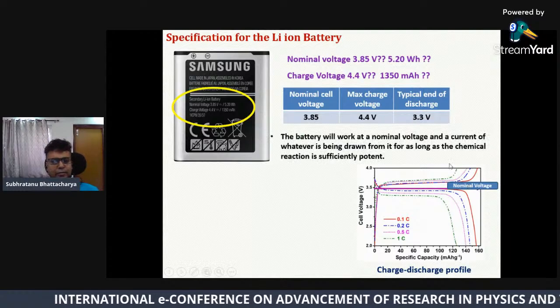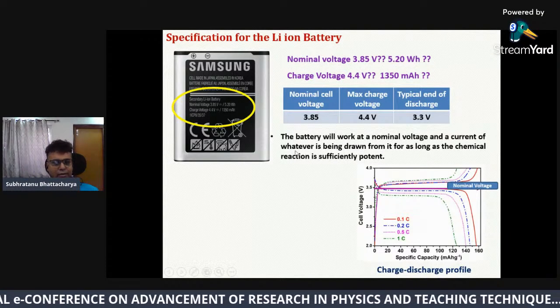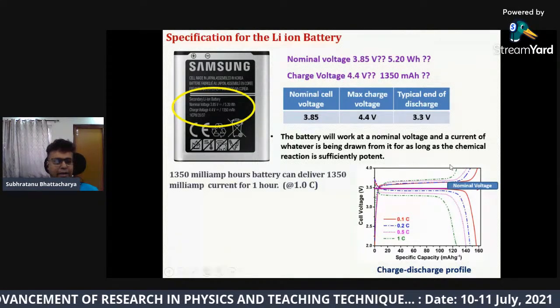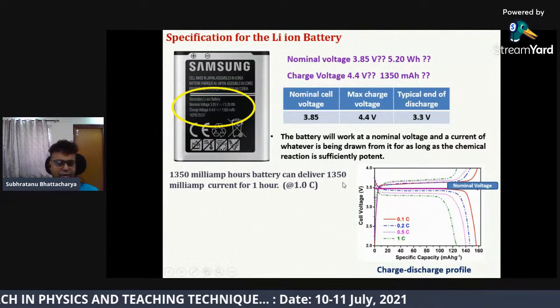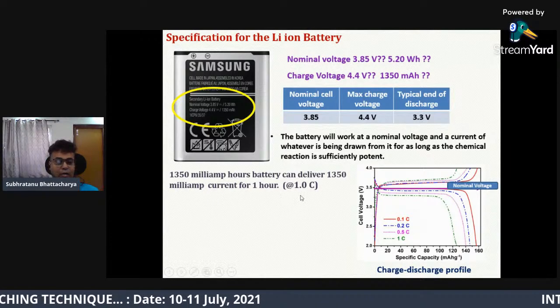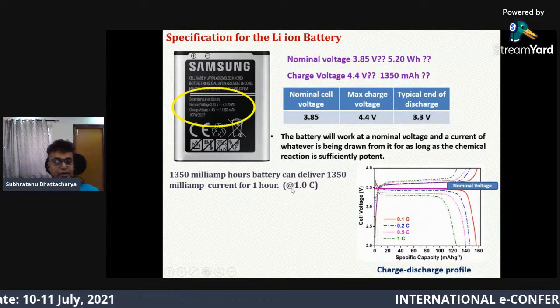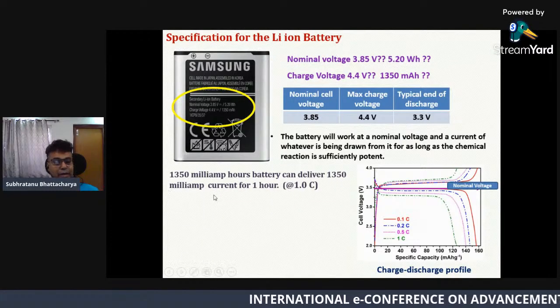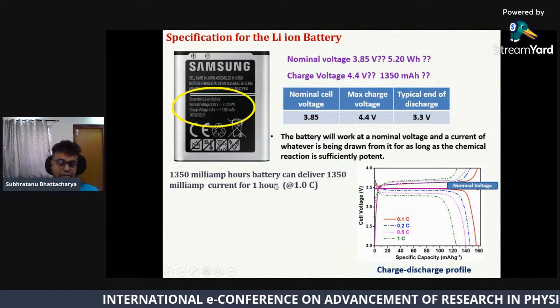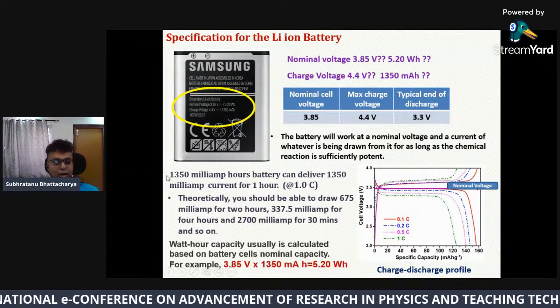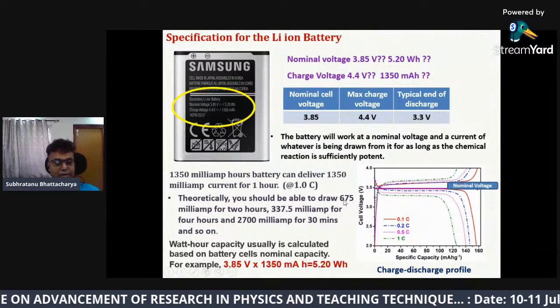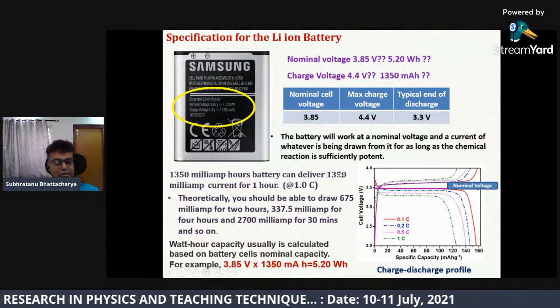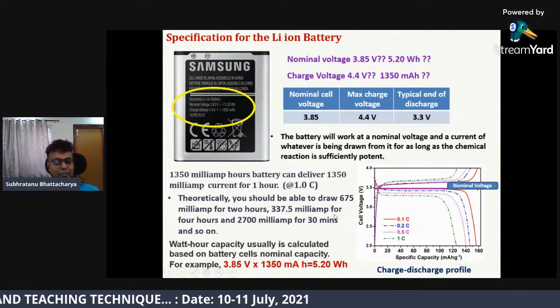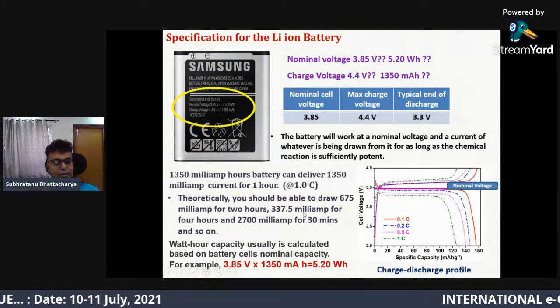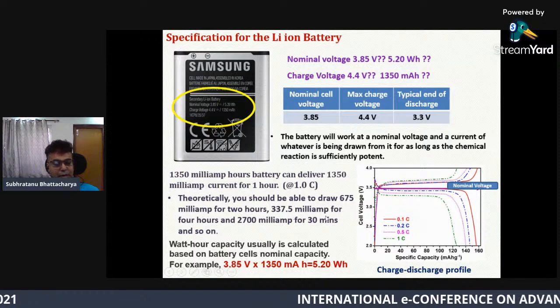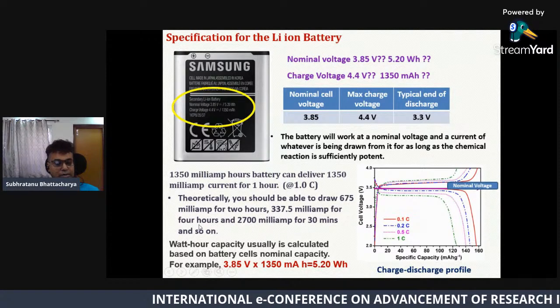The battery will work at a nominal voltage and a current of whatever is being drawn from it, and a 1350 milliampere hour battery can deliver 1350 milliampere current for 1 hour. This is called 1C rate. It means if you use 1350 milliampere current, you will discharge it within 1 hour. If you use 675 milliampere, just half, then you can increase your battery life to 2 hours. This is called 0.5C. And if you use 337.5 milliampere, then you can get 4 hours of battery life.